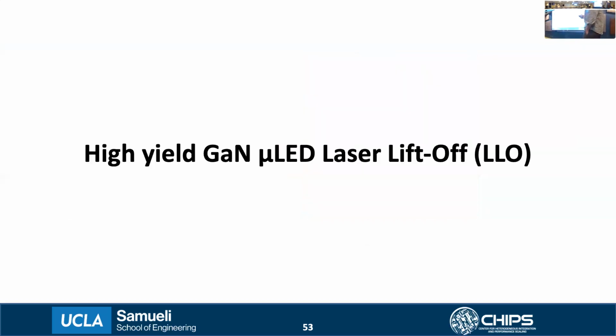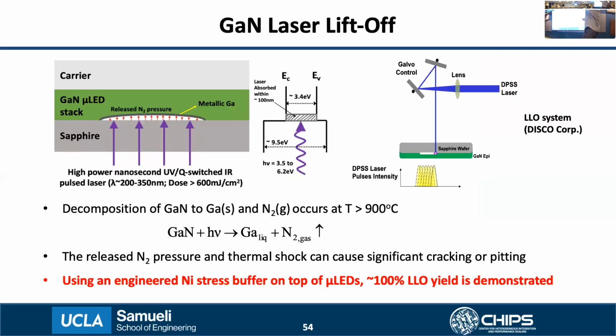Okay. So now let me talk about some of the work we have done with high yield gallium nitride micro-LED laser lift-off. This chart summarizes how the GaN LLO process happens. This is a typical cross section which shows the sapphire substrate at the bottom, which is polished on the backside, then the GaN micro-LED stack, and then the glass carrier at the very top. A high power ultraviolet excimer or a Q-switched IR laser, third harmonic, is shone from the backside of the sapphire substrate. It passes through the sapphire without much attenuation because of the large band gap of sapphire, but when it hits the interface of the GaN and sapphire, it is absorbed within about tens of nanometers.